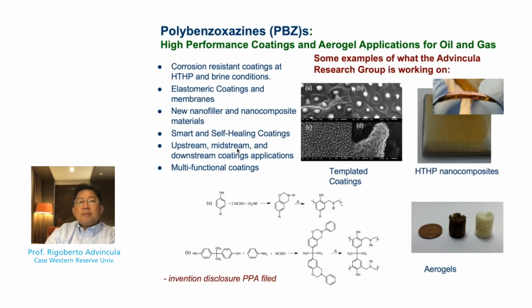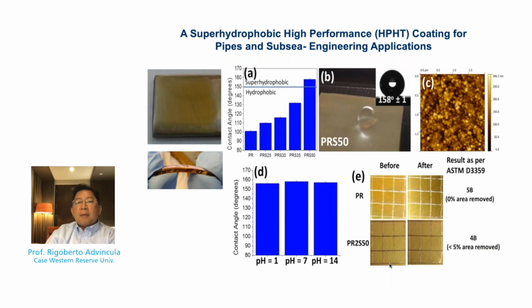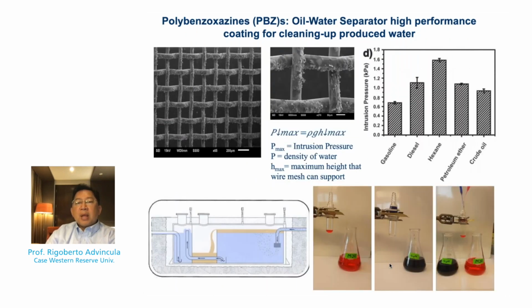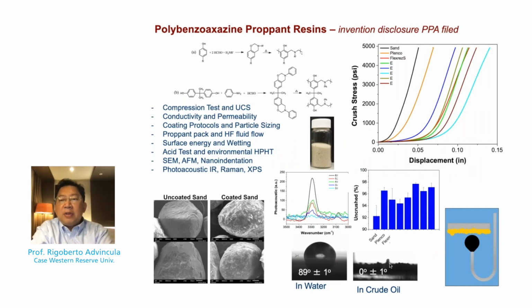Okay, so let me close by pointing out that one of the compositions we have done is based on the use of polybenzoxazine. Now, polybenzoxazine chemistry is a thermoset chemistry with a higher temperature rating. We've actually used it for coatings that can be used for oil and water separation or the formation of aerogels. As can be seen here, the benzoxazine ring is simply opened up by heating to produce a thermoset with a high degree of cross-linking. Now, skipping this curve, let me just focus on how we have proven this concept.